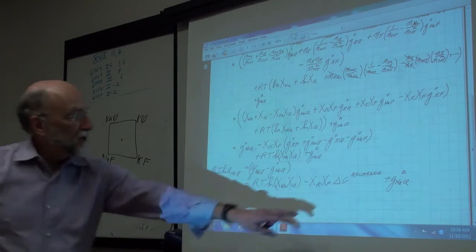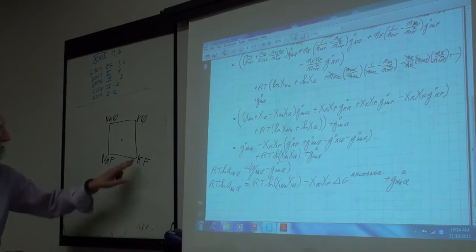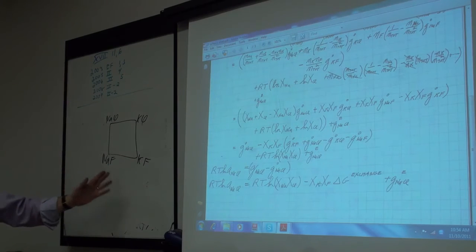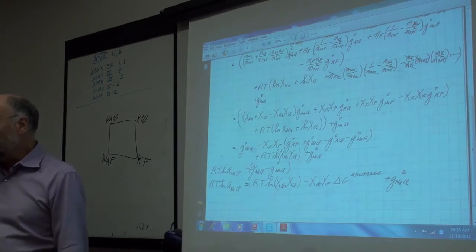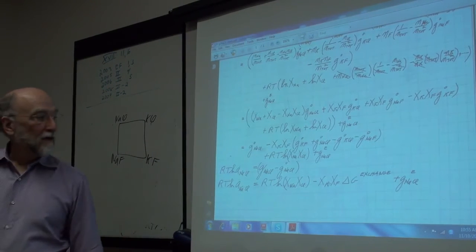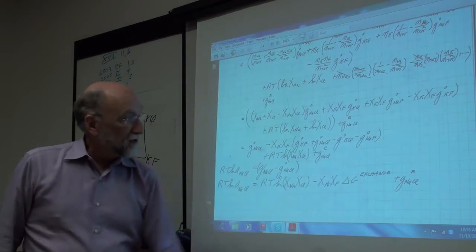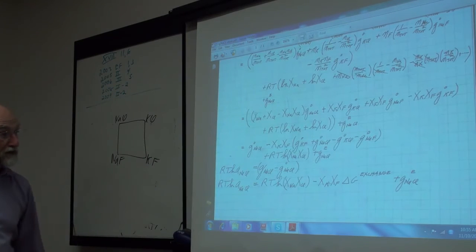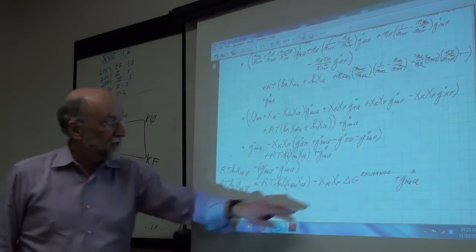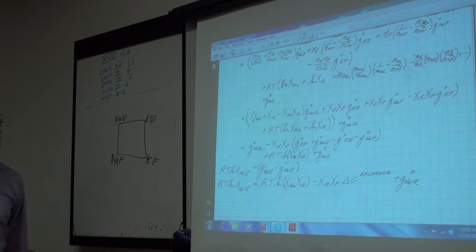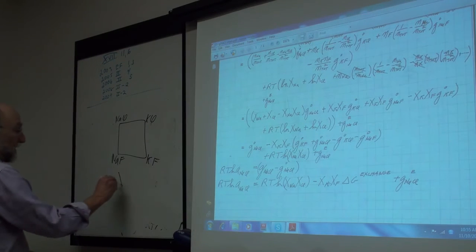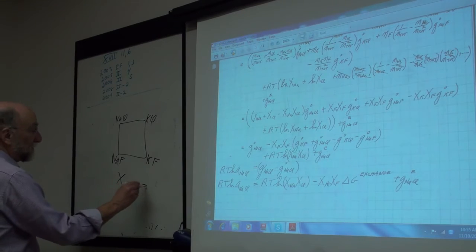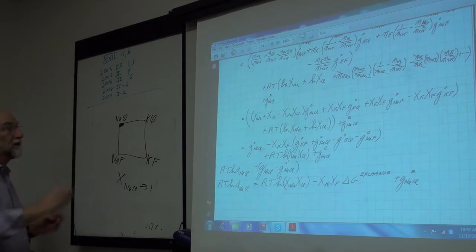Okay, so if your exchange Gibbs energy is 0, then the activity of sodium chloride is just X sodium times X chloride, the product of the site fractions. If your delta G exchange is negative, we went through this before, then you have a positive term along here, which brings up the liquidness and so on. But let's suppose now that X sodium chloride, the mole fraction of sodium chloride, is approaching 1, so you're in this region up here. You're around sodium chloride.